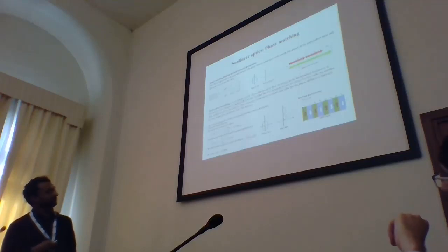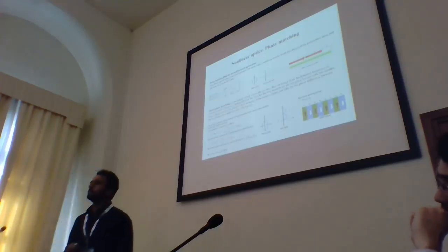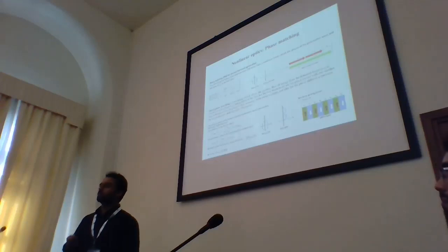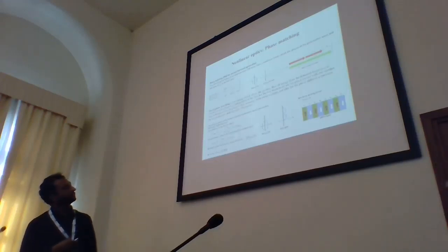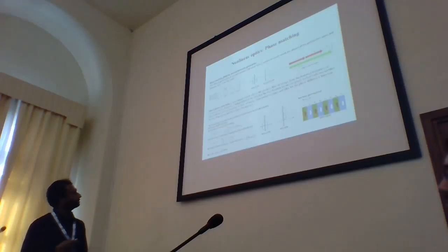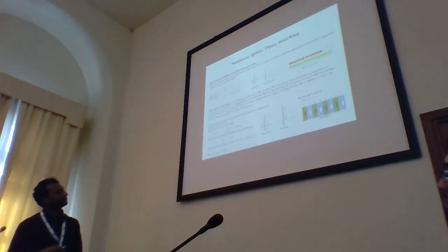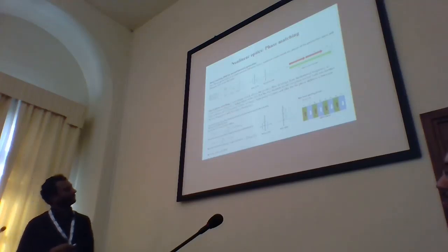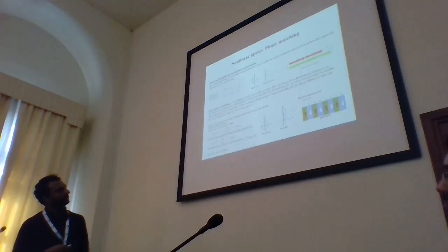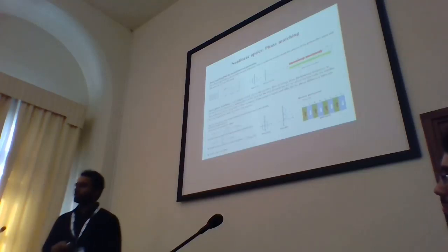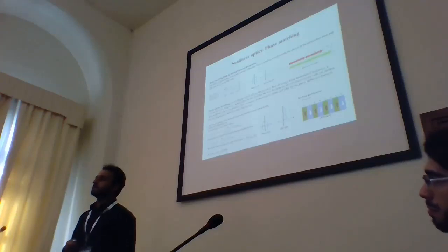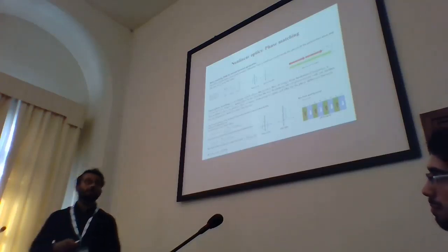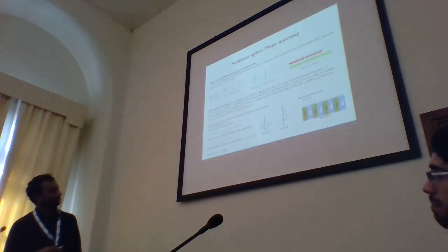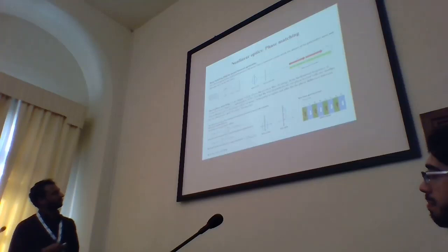So technically there are ways that you can try to reduce this phase mismatch, and that eventually leads to optimum conversion efficiency. You can produce more of your second harmonic depending on how much you can reduce this phase mismatch. One of the prominent ways is quasi-phase matching, in which we periodically engineer the nonlinearity of your crystal such that once your fundamental beam sees one coherence length, the nonlinearity flips its sign, and what you see is a field that is progressing, and you can enhance your second harmonic generation.